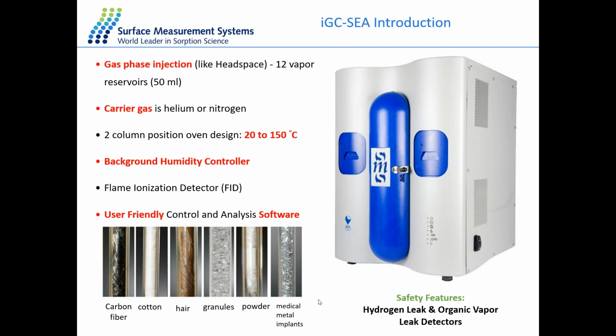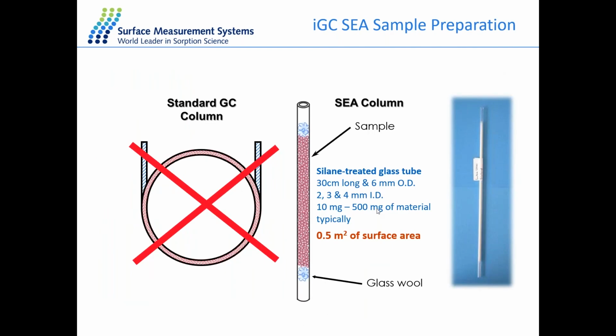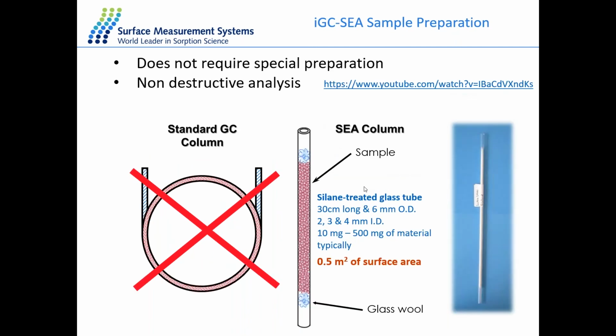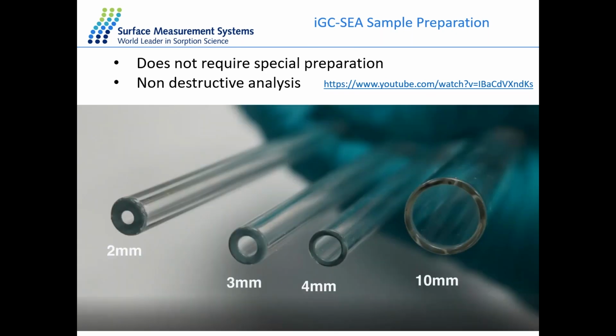The iGC is a very versatile technique. Here are some examples at the bottom of what we have managed to pack into a column and analyze successfully. So we have carbon fiber, cotton, hair, some granules, some powders, and even some medical metal implants. For sample preparation, what you usually have is a sample column, which looks like this. And this is much more straightforward than packing a GC column. Effectively, with this silanized glass column, you would plug in some silanized glass wool, funnel in your sample of interest, and close off with some silanized glass wool. We also have a nice U-shape clip to show how straightforward it is to pack a column.